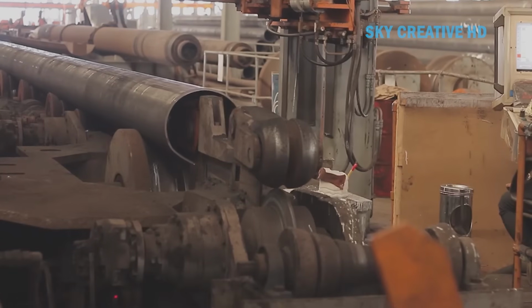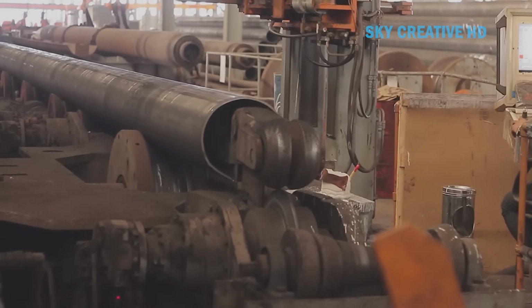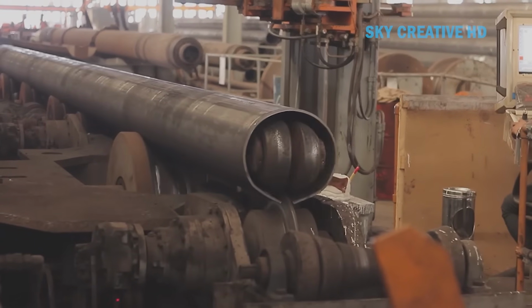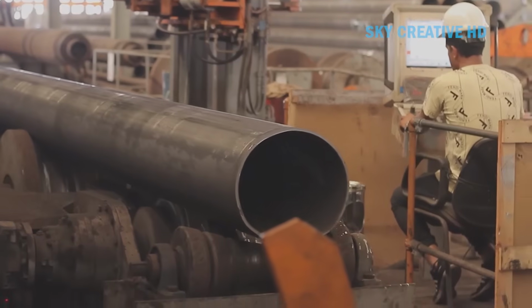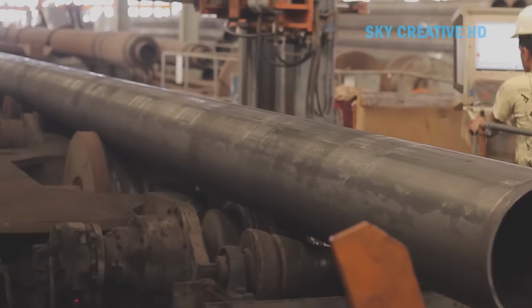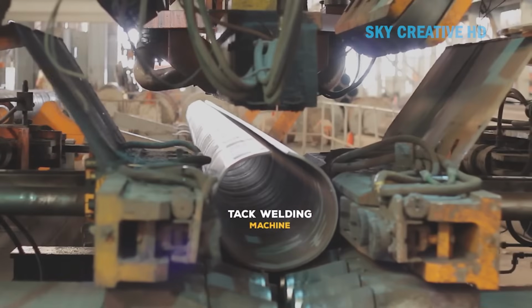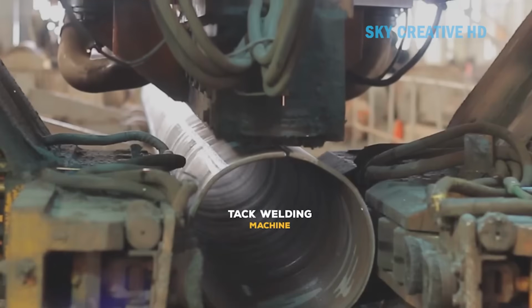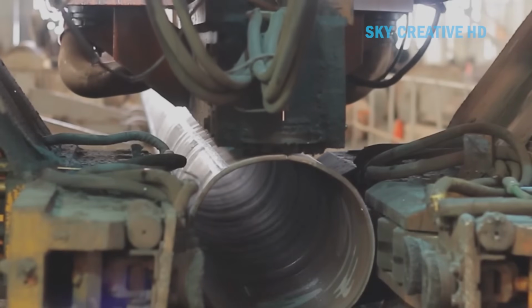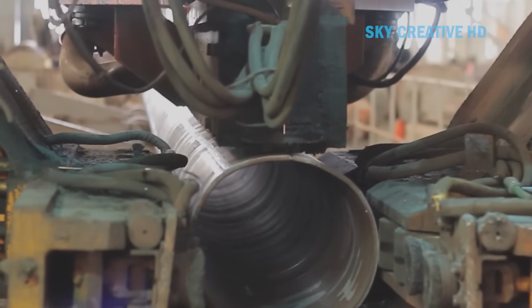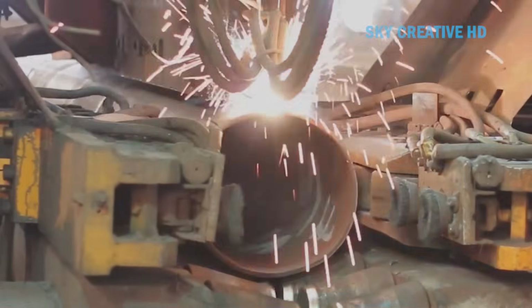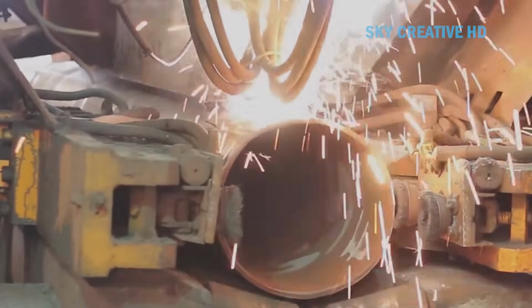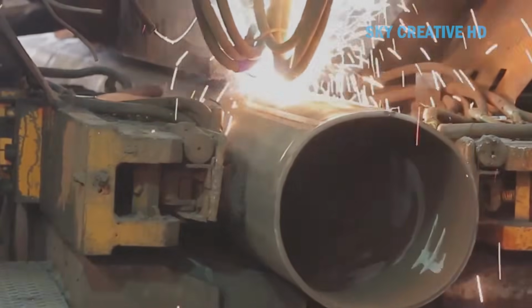Edge preparation follows, where the steel strip edges are machined to exact angles that will ensure perfect welding. The cutting equipment uses plasma torches operating at temperatures over 40,000 degrees Fahrenheit, nearly 4 times hotter than the surface of the sun. Computer-controlled systems guide these torches with precision that keeps the cut edge straight within 0.020 inches over the entire length. The forming process is where the flat steel transforms into pipe.